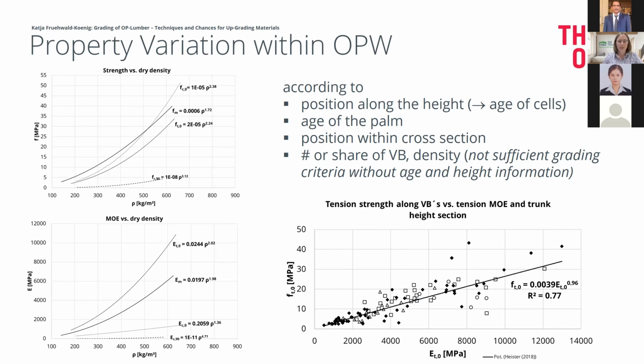The position within the cross-section at a certain trunk height has an influence on the mechanical properties. This is because the number of vascular bundles per unit area and the area proportion of the vascular bundles is rising from the center to the periphery. Therefore, the density and the mechanical properties are rising from the center to the periphery of the cross-section. But without knowing the age of the palm and the position along the height, the number of vascular bundles per square unit or the share of vascular bundles is not a sufficient grading criteria. And the density is much easier to determine than the number or share of vascular bundles.